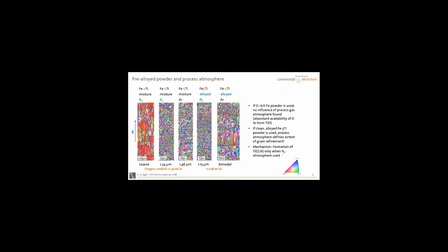We do see, I mean, we still see a lot of grain refinement in the case of processing under argon, yes. So here you have a kind of a bimodal microstructure with some elongated grains and columnar grains. And of course, these are definitely much finer than, for example, this microstructure over here with the 2% titanium. But you see a difference. You don't have complete grain refinement as in the case of processing under nitrogen if you process under argon.